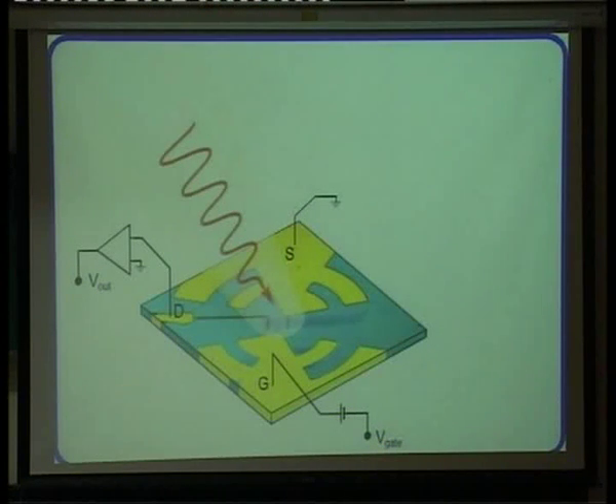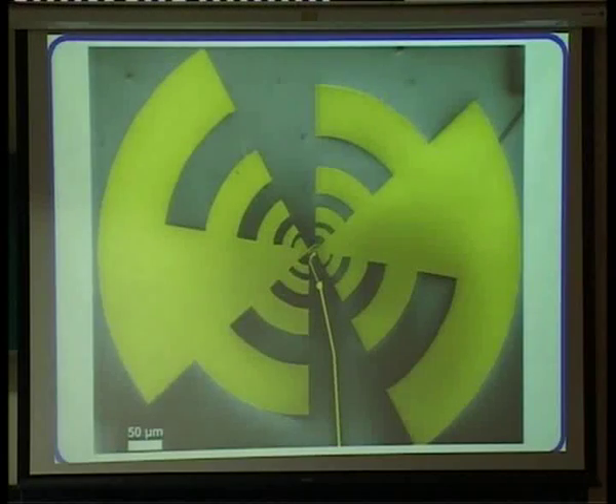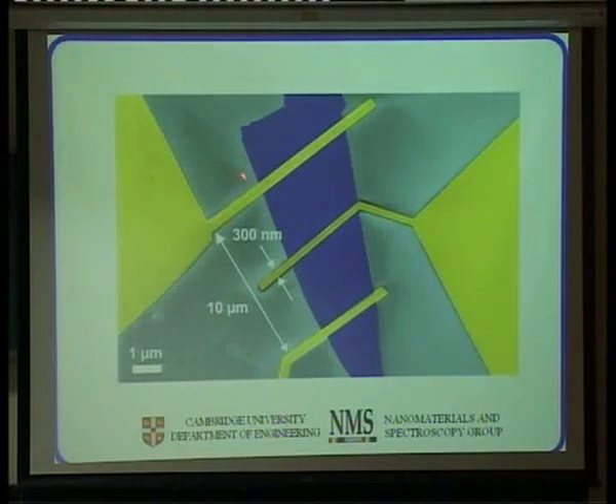Again, cutting a story short, we have created a transistor, an FET with graphene, but we have coupled it with light via an antenna. This is a log periodic antenna. A log periodic antenna can be designed in order to be resonant at different frequency. So the length of these little spikes defines what frequency the antenna works with. And that's the actual real device. So that's the graphene you cannot see in the middle. That's the antenna. And these antennas are designed to interact with light in the terahertz spectrum. The graphene is in the middle, and there's a source drain at the top gate.